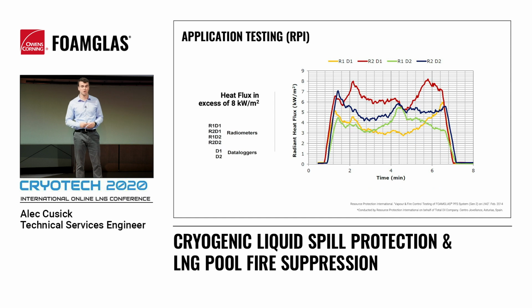Here you can see the results of those 4 radiometers over the duration of this initial test. You can see it fluctuate quite a bit, but in general, we're looking at readings of between around 3 and 8 kilowatts per meter squared from each radiometer around the corners of the pit.